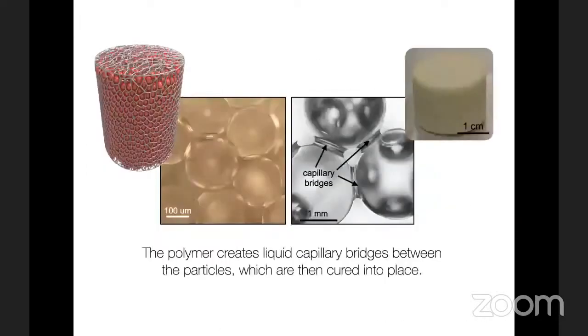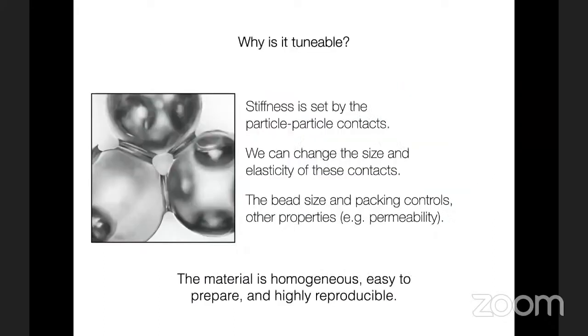Sorry. All right. So these are just some pictures of it at different length scales. And you can see that the material looks like what you would expect if you had two grains of sand that were wet, that the water would go to a bond between them, and instead of being something wet, these are now solidified into place. If you tear them apart, they won't reform. And so this is a material that we call a tunable cohesive granular material because we can set the stiffness of the entire particle assembly by playing with the particle-particle contacts.